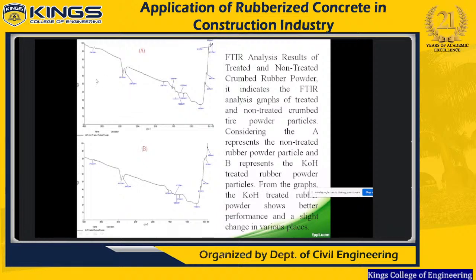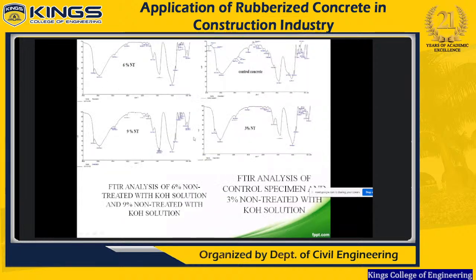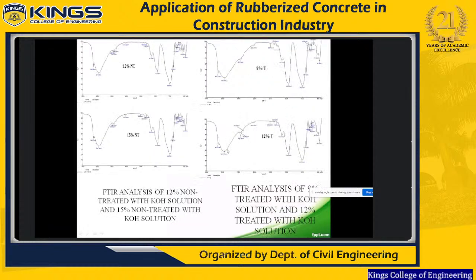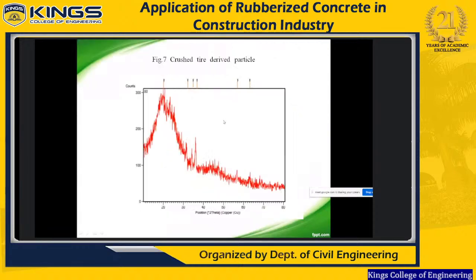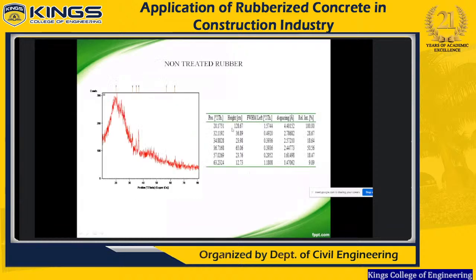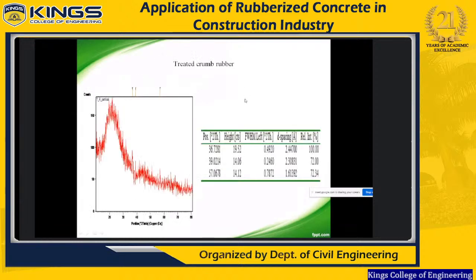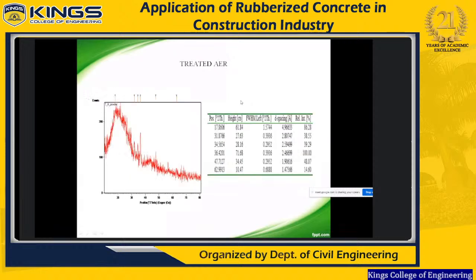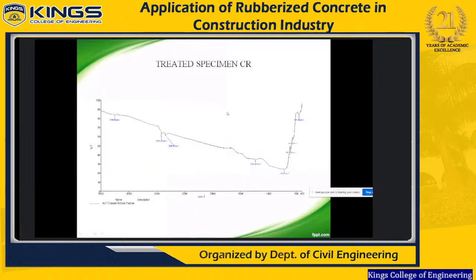So FTIR analysis is carried out at different ratios here, 6% and 9% of treated and non-treated. Based on the peaks, we have identified that the chemical composition of the rubber varies. Another is non-treated rubber, also seen here, and treated crumb rubber. The graph shows what the actual situation is before casting the concrete, and after casting the concrete, how the chemical composition is present in the concrete.